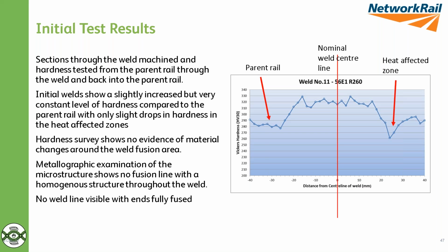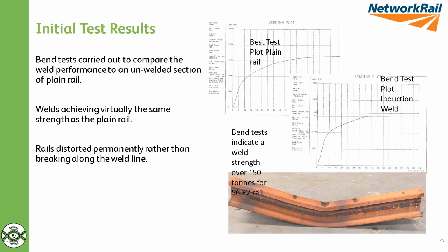So some quite pleasing initial results from the work that we've been doing, which I'm hoping, if successful, with these are effectively the first site trials. We've seen some very good bend strength, and in some cases the welds have been as strong as, effectively achieving a very similar performance to, the parent rail. So we've seen the rails bend rather than fracture. And when you actually look at the microstructure, there is very little to see. To all intents and purposes, it looks like a continuous length of plain rail.